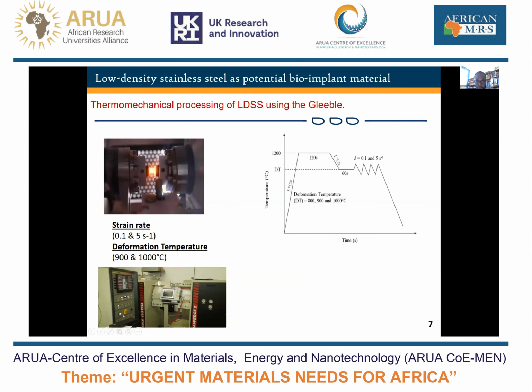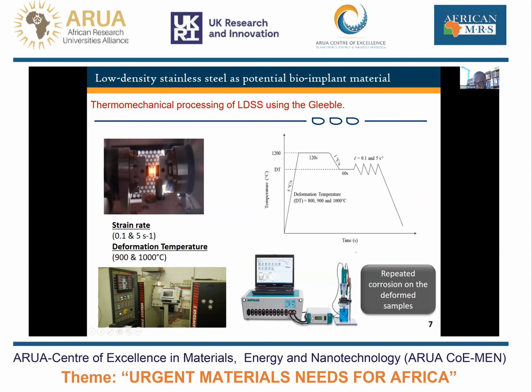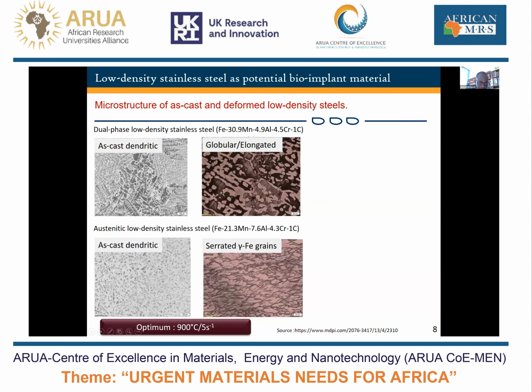So what we did next was to carry out thermomechanical processing using optimized parameters, popularly reported temperatures and strain rates for deforming this grade of steels based on literature. After that, we carried out corrosion testing again on the deformed sample to see if there is any difference in terms of reducing the pits, and maybe eliminating the pitting that we find in the dendritic region. This is just a typical as cast dendritic microstructure, and I'm giving you an example of two different alloy systems among the wide range of alloys that we produced. You can see this dendritic configuration in both cases.